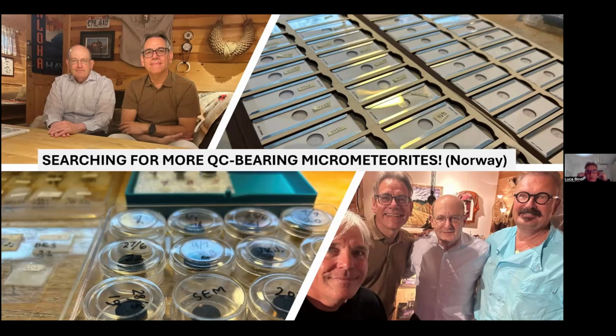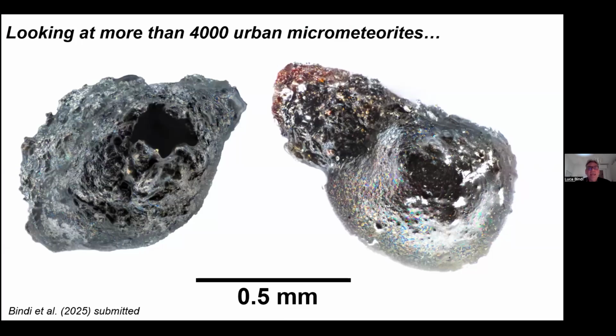So together with Paul, we spent 2 weeks in Norway, and we searched among his collections, and we identified several possible candidates, including this one. And so these are 2 candidates which actually turned out to be not only promising, but actually containing copper aluminum alloys. And this selection was mainly based on the morphology of the materials. Look at this scoriaceous nature, or for example, the presence of particular luster, or presence of metallic silvery flakes on the surface, something like this, for example, okay?